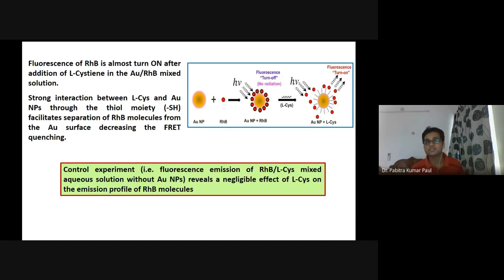That is the fluorescence emission of this mixture, rhodamine B and L-Cysteine mixed in aqueous solution without gold nanoparticles, reveals a negligible effect of L-Cysteine on the emission profile of the rhodamine B molecule. That is, without the gold nanoparticles, there is no change in the emission property of the rhodamine B molecule. So, in this process, this nanoparticle has a fantastic utility, or significant interesting utility, to measure the concentration of L-Cysteine.